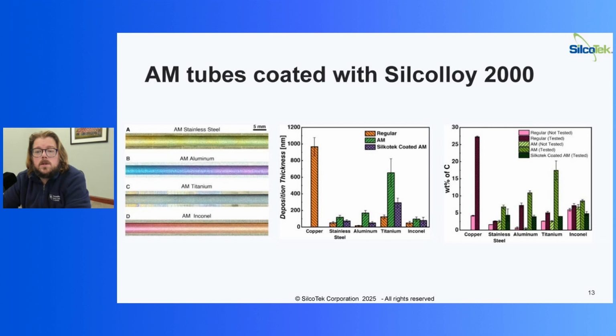So that's where Silcolloy 2000 really came in to help out. On the left-hand side here, these are all the tubes that are coated with Silcolloy 2000. You can see the nice pretty colors on the Inconel and the aluminum. Sometimes our coated tubing isn't that pretty. Sometimes it has this gold color you can see on the stainless steel. Sometimes it almost looks like it's uncoated if it's just the right thickness, like you can see on titanium.